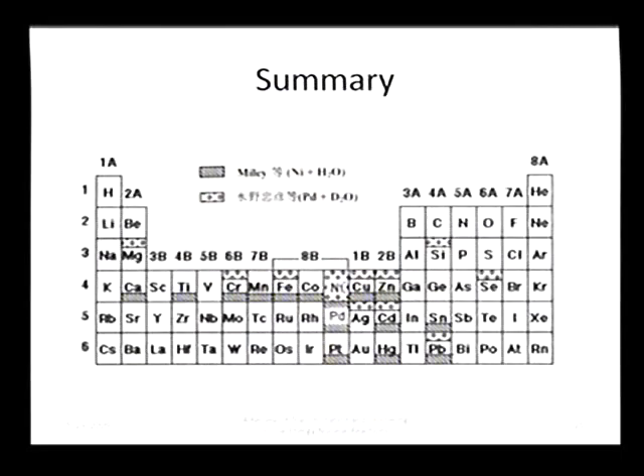This is more or less a summary of the elements. If you look at the periodic table, basically in Miley's experiments, it was calcium, titanium, chromium, manganese, iron, cobalt, copper, zinc, etc. There was some overlap with earlier experiments. And other experiments showed magnesium, silicon as potential differences in materials that were created.